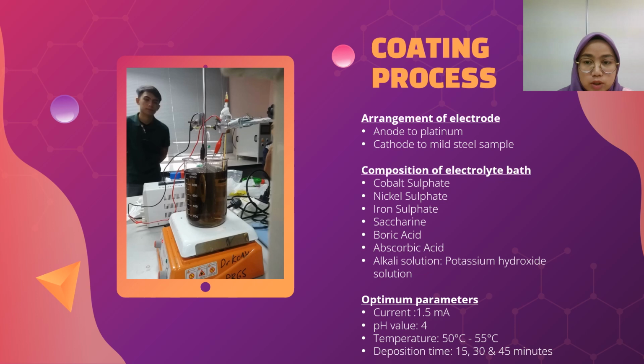The arrangement of electrodes for the electroplating process is that the anode is connected to platinum while the cathode is connected to the mild steel sample. The composition of the electrolyte bath is cobalt sulfate, nickel sulfate, iron sulfate, saccharine, boric acid, and ascorbic acid. Potassium hydroxide solution is used to increase the pH value of the electrolyte bath.